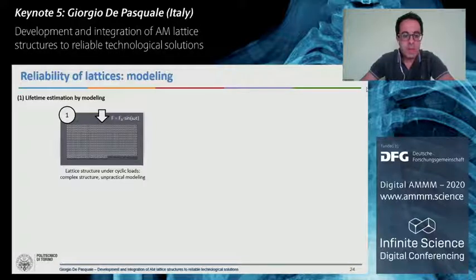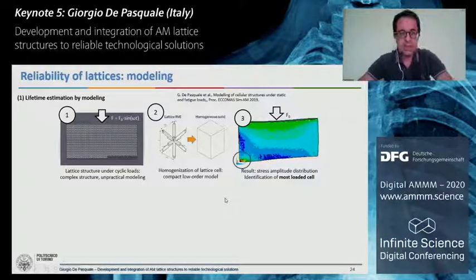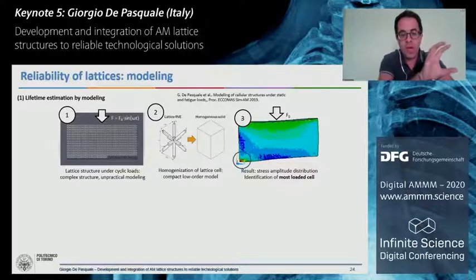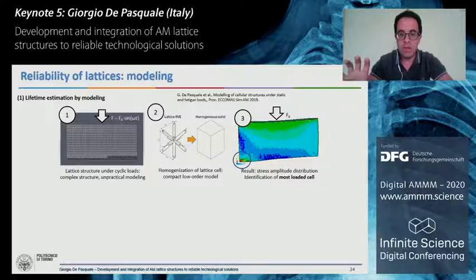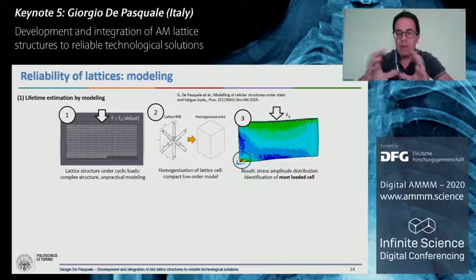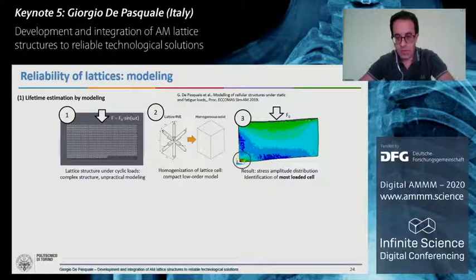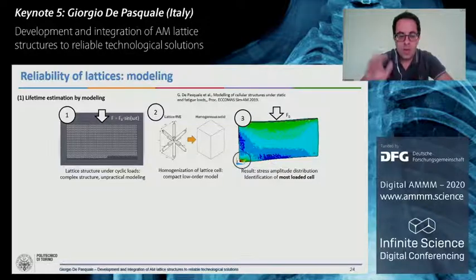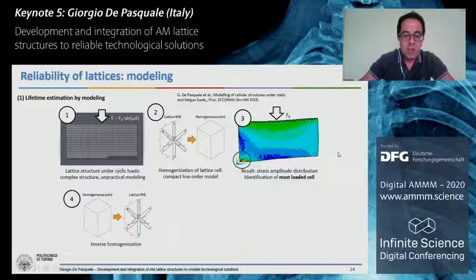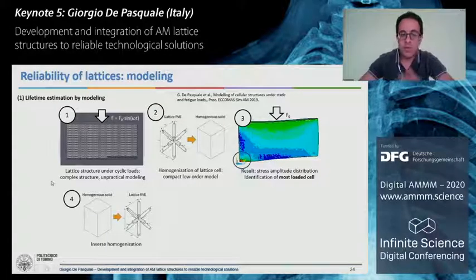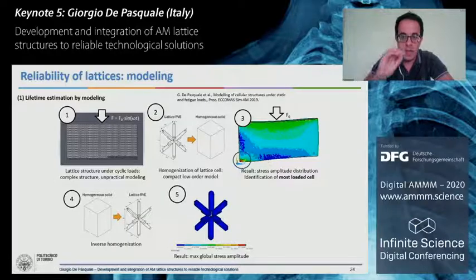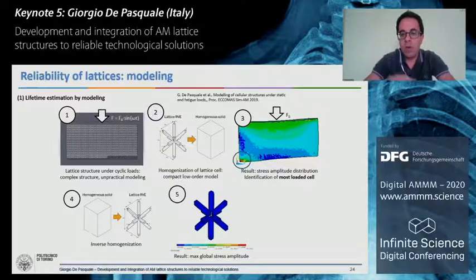Let's start with something about modeling. If we consider a lattice structure where a cyclic load is applied, the shape is complicated, so it's not easy to use FEM models. So the best way is to apply the homogenization method to convert our lattice cell into a homogeneous solid material, so a brick element, then to rebuild our volume and calculate the stress distribution inside it. Then we can identify only the most loaded cell. We don't care to study all the cells, only the most loaded one is enough. We apply the inverse homogenization criteria on this most loaded cell to rebuild the original shape of the real lattice cell, and we can investigate the stress distribution on the most loaded cell of our lattice structure.